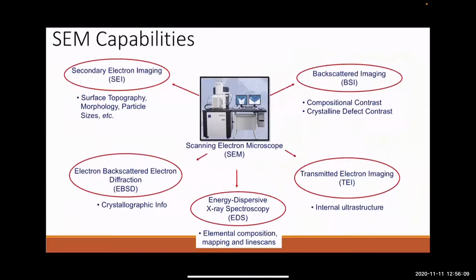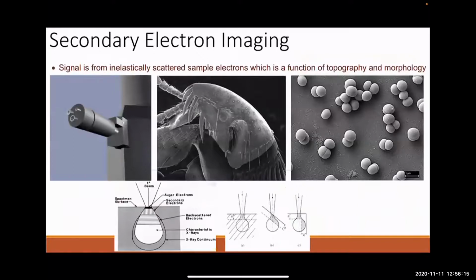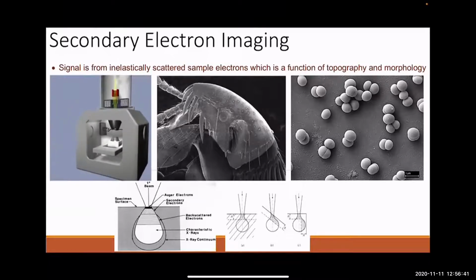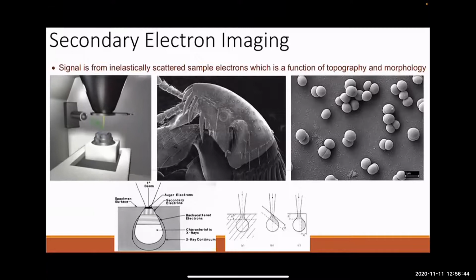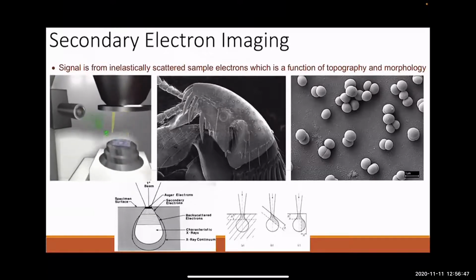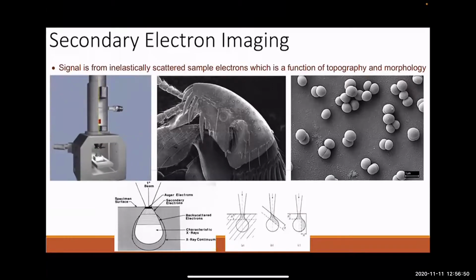So much like the TEM, you've got different imaging capabilities here. Secondary electron image is probably what you see in the literature when you're perusing a paper and you see an SEM image. Probably greater than 90% of the time, what you're looking at is a secondary electron image, because the number of secondaries, remember that's sample electrons that are being scattered out, is a large function of the topography of your sample, okay? So it's good for basically getting an image that is very much like what you'd see with a reflected light microscope, even though the image construction is very different. The image that you get can be interpreted in the same way.